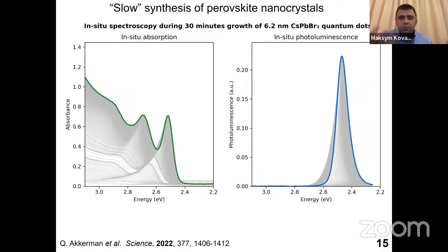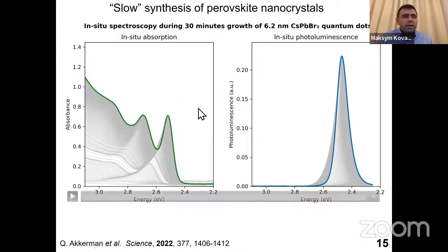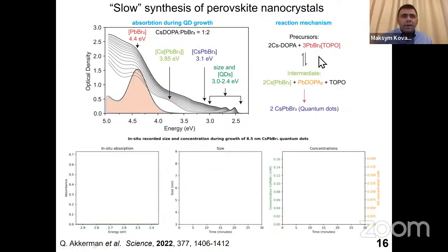So you may ask, what did we change? The idea here is that we avoid using any amine in the system, because when you have amine, it will become ammonium. And if you have ammonium, you will need to have a counter ion, which is lead bromide, cesium lead bromide 3 minus, lead bromide 3 single minus, which is too reactive. So you had better not have active ionic species in the solution. You should go as molecular as you can, and therefore you will have much slower nucleation and growth.